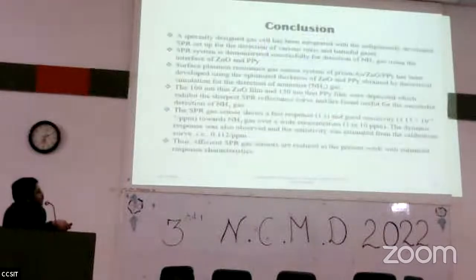We have also taken the transient or dynamic response for this concentration variation. Again, it is observed that for 0 to 10 ppm, it shows linearity. This can work as an SPR gas sensor. So in conclusion, the thicknesses of ZnO and polypyrrole were optimized, then their response and sensitivity were observed. So this works as an efficient SPR gas sensor.